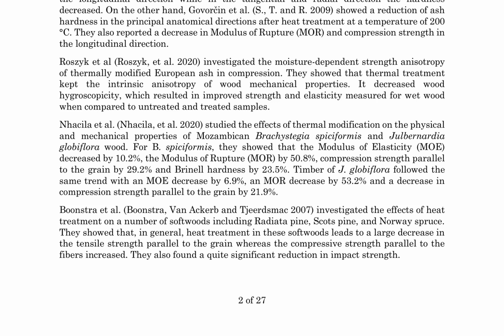Moreover, thermal treatment has been found to maintain the intrinsic anisotropy of wood mechanical properties, leading to improved strength and elasticity in wet wood compared to untreated and treated samples. However, significant decreases in modulus of elasticity, modulus of rupture, compression strength parallel to the grain, and Brinell hardness have been observed in certain wood species, such as Mozambican Brachystegia spiciformis and Julbernardia globiflora.